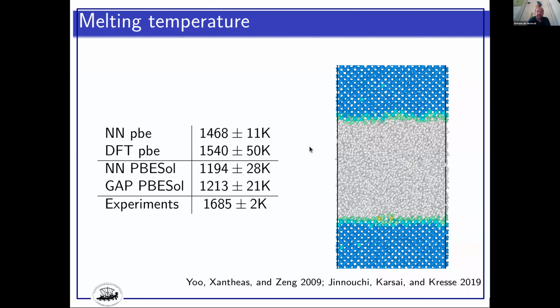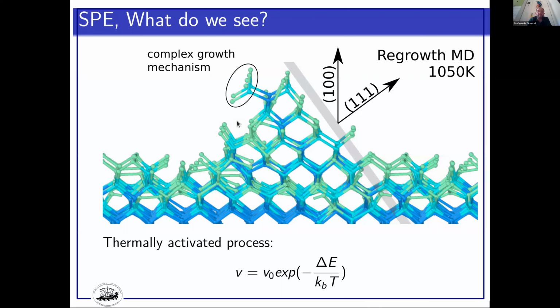Yeah, the experimental result is higher, but at least PBE gives a decent melting temperature, and we could model this recrystallization, and we see the formation of some growth motif, some pyramid that is oriented in the 111 directions. The faces are oriented in the 111 direction. These are models that were proposed experimentally, but were not, let's say, confirmed. We are still working on that, but it's an interesting feature.